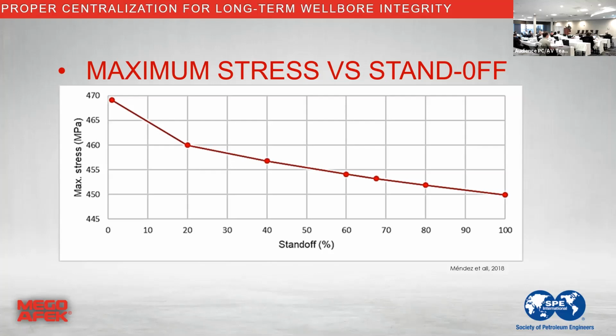You don't have to try to have 100% standoff. That's what they're saying. 67%, that vicinity should be considered good standoff, should allow full coverage, should allow minimum stresses in your wellbore, should allow minimum ability for chemical attack, CO2 attack, etc. So if you're within that number, you're good. Something that we as centralization people don't necessarily mention is that the better the standoff, that is the closer to 100%, the higher the ECD in your system. So if you're also trying to combat or lower ECDs to minimize losses, the better it's centralized, the higher your ECDs.